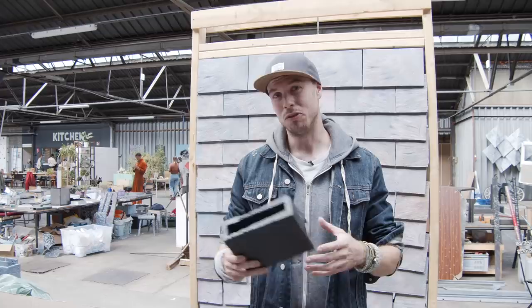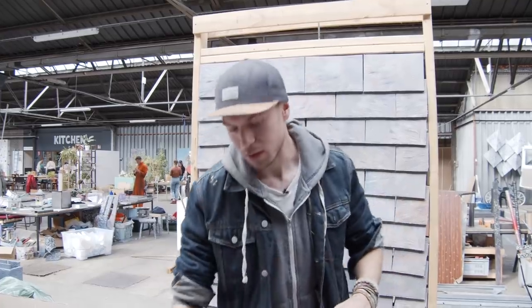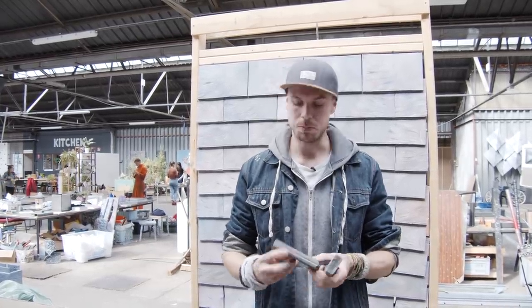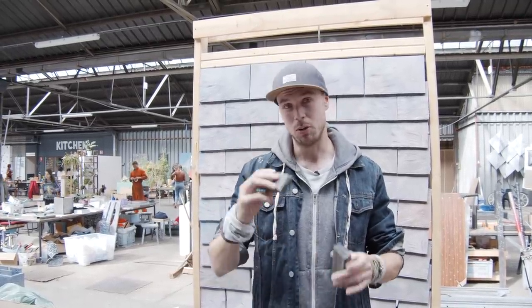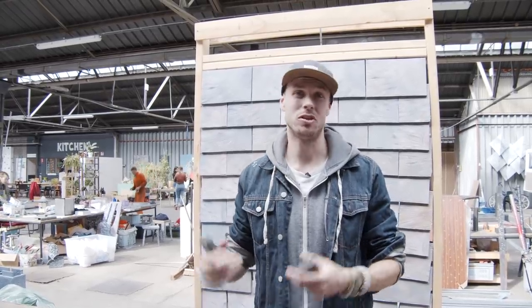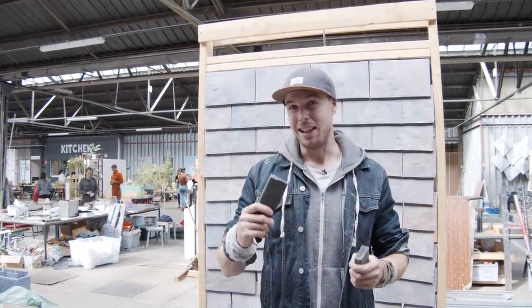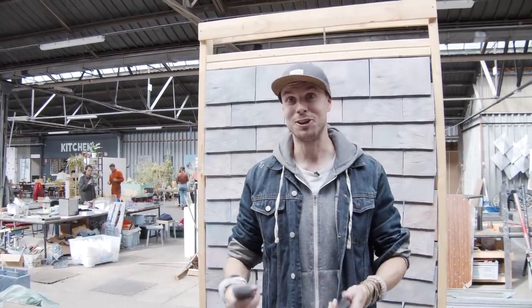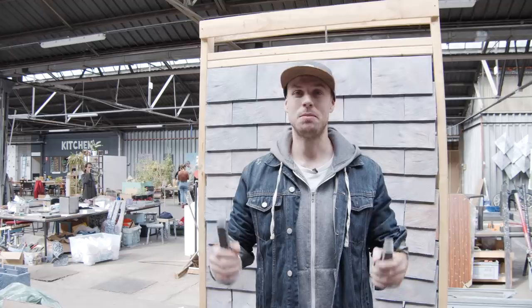But there's a lot more work involved when we talk about bricks other than the shape. What we've been really working on is: what if your plastic is really dirty, what if it's come from the beach, maybe straight from the ocean or landfill, maybe it's not all one type of plastic. In one of these experiments, we started working with polypropylene and added sawdust to see how it would affect the bricks — as if it was dirt mixed in with the plastic. Adding sawdust actually made it a little bit less flexible and made it shrink less. In our case, it made it harder to get out of the mold, but if you think about that shrinkage, each one of those blocks was exactly the dimension we wanted it to be.